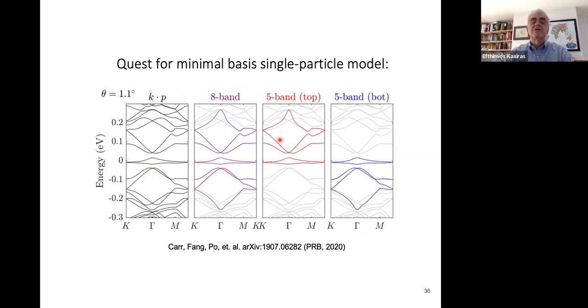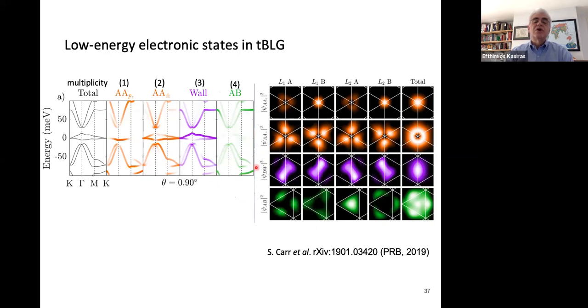Here's a smaller set of 5 bands, just the flat ones near the Fermi level and 3 above, or the flat ones near the Fermi level and 3 bands below. This is about as small as you can get with a basis, because below that you start losing the essential physics. Why is this? Because the 2 bands right here in the middle are not enough, as I alluded to earlier. We know this because we also know the wave functions of these bands. So here's again the total band structure, and here are the projections of the bands on different wave functions.